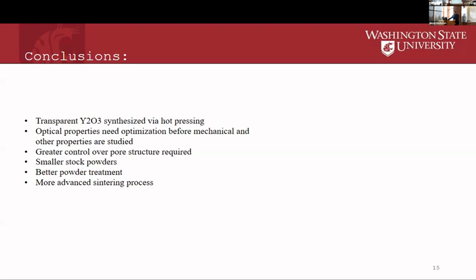The way we intend to go about doing that is by utilizing smaller powders. We have nano powders that we're intending to use in our next line of synthesis. The challenge with using nano powders is that they're much more difficult to work with—they tend to agglomerate a lot more, and they don't flow nearly as well. So to counteract that, we're going to improve our sample powder treatment, and we're also going to employ a more advanced sintering process with more holds to try and improve our densification.